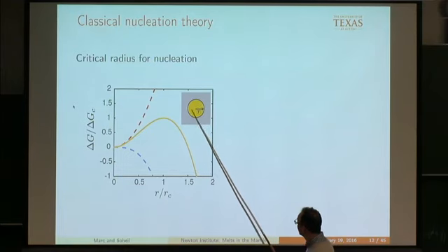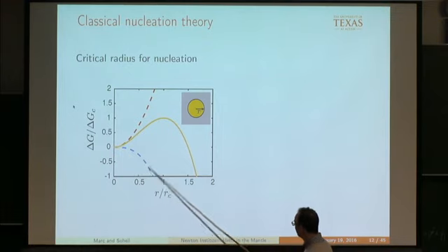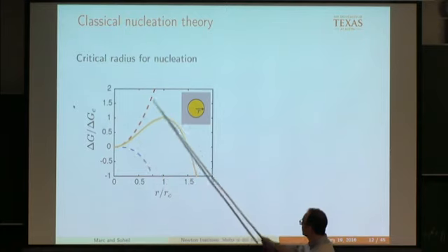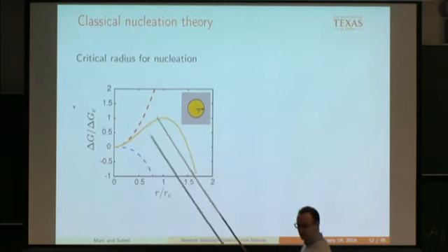you're going to nucleate it because the volumetric Gibbs free energy of this phase is lower, and so this would reduce the volumetric term, which goes as r cubed, reduces the overall free energy, but you're creating a new interface, and that of course goes as r squared, and that adds energy.